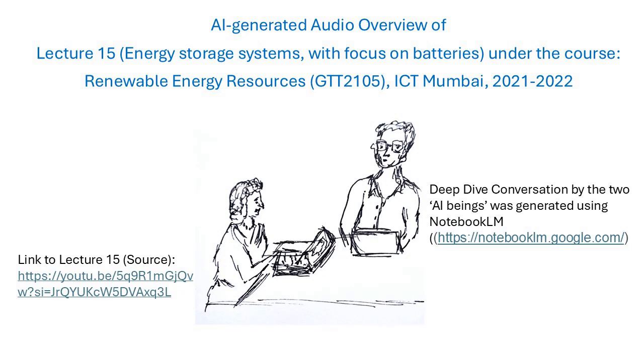And it was good enough. He looked for cathode materials that could give even higher voltage. And he landed on metal oxides, specifically lithium cobalt oxide, LiCoO2, also layered, also using intercalation. But the different electronic structure gave a much higher voltage, 3.5, maybe 4 volts. Huge step up. It still had that lithium metal anode. And that was the big problem.